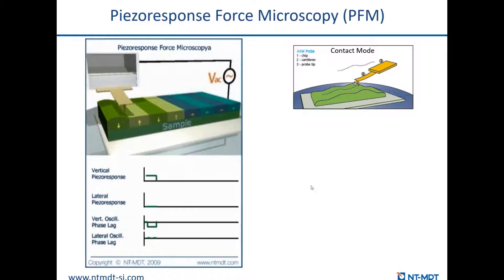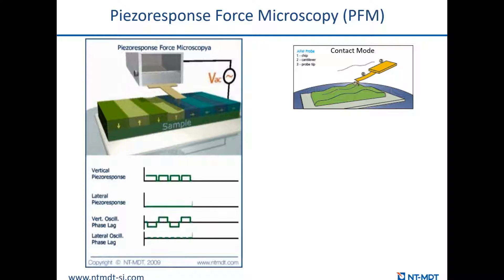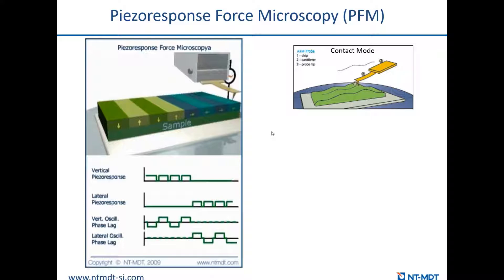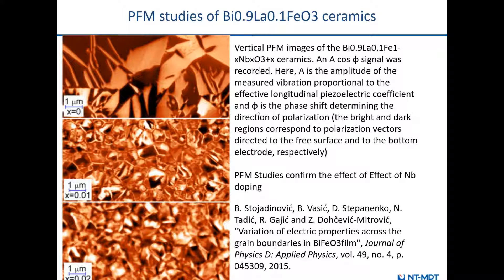The next technique is Piezoresponse Force Microscopy (PFM), because piezoelectrics are good representatives of smart materials. In PFM, we apply alternating voltage between tip and sample while the tip is in contact. If there is polarization or domain structure on the surface, we will see a response in vertical or lateral direction. There are thousands of works published on this topic. For example, PFM domain imaging of piezo ceramics was done to see the dependency of material on niobium doping, showing that increased doping dose decreases the size of domains.